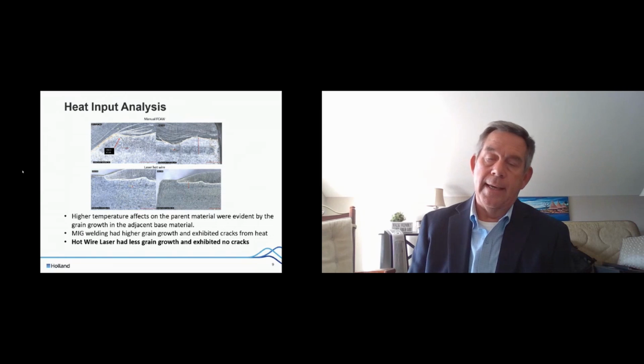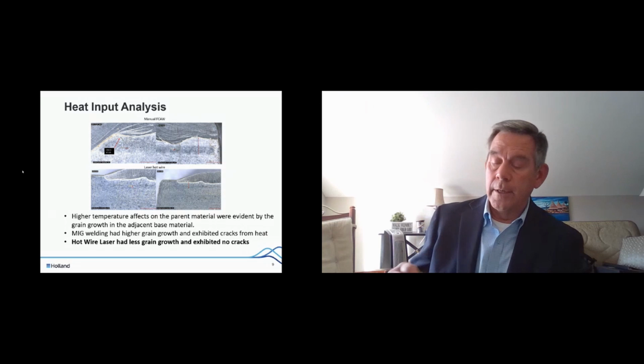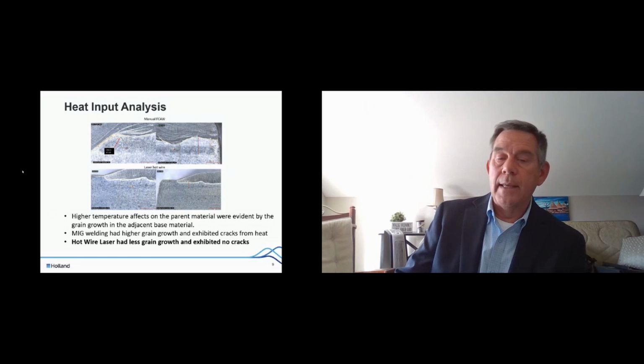The advantage with laser welding is that it puts so much less heat into the base material. In that particular case, the lower graphs show the laser process had significantly less grain growth and there was no cracking in the material below the weld. So excellent results under the heat input analysis.